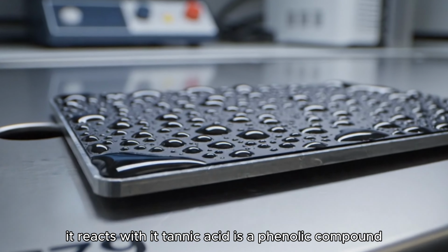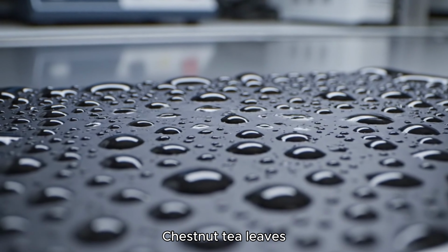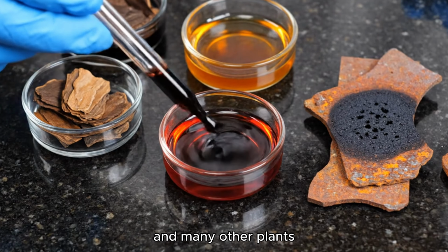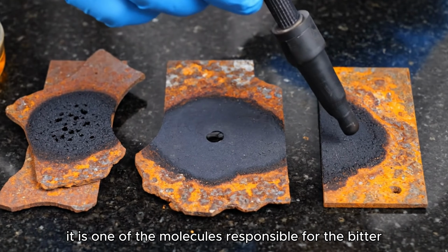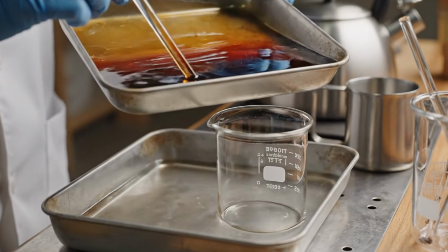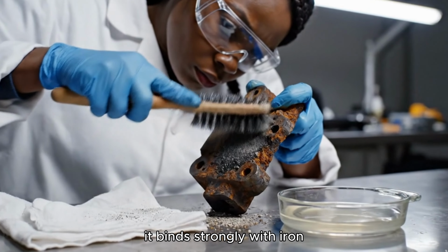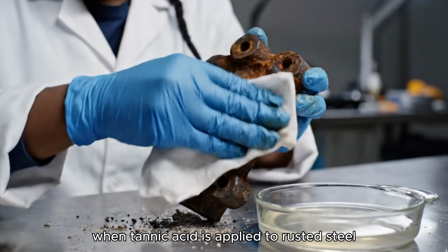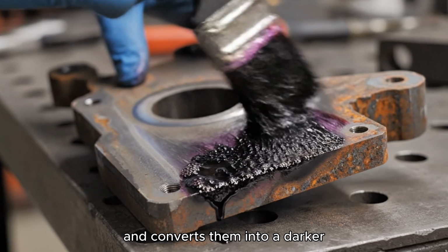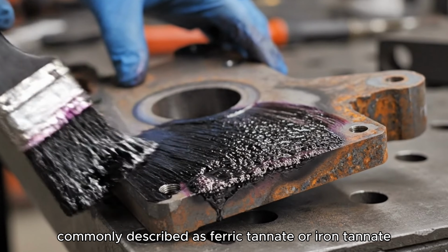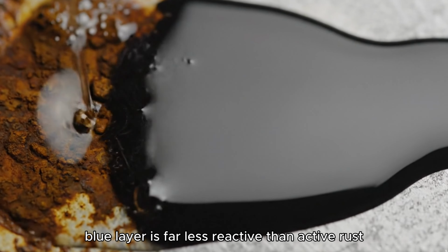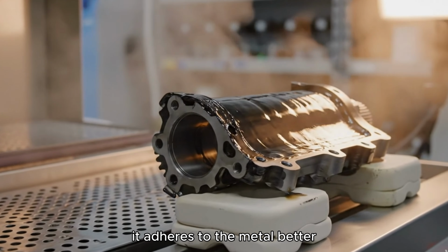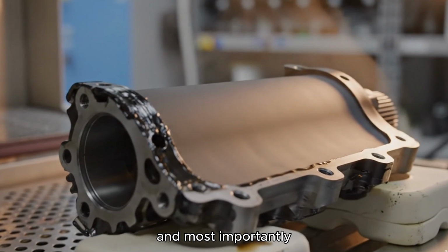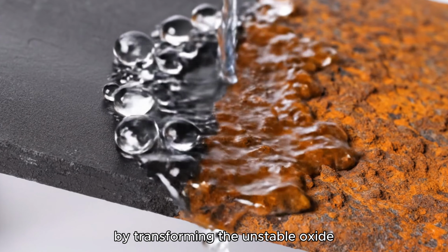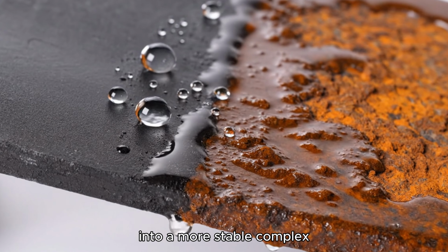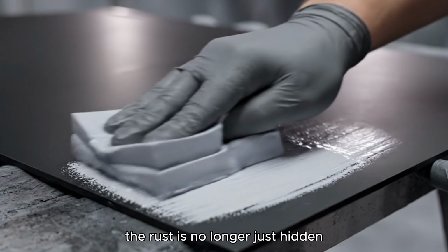Tannic acid is a polyphenolic compound found naturally in oak bark, chestnut, tea leaves, grape skins, sumac galls, and many other plants. It is one of the molecules responsible for the bitter, astringent character in many plant materials. But chemically, it has another remarkable trait: it binds strongly with iron. When tannic acid is applied to rusted steel, it reacts with ferric oxides on the surface and converts them into a darker, more stable material, commonly described as ferric tannate or iron tannate. That black-blue layer is far less reactive than active rust. It adheres to the metal better, it is more water-resistant, and most importantly, it interrupts the runaway corrosion cycle by transforming the unstable oxide into a more stable complex. That is the real breakthrough. The rust is no longer just hidden, it is changed.